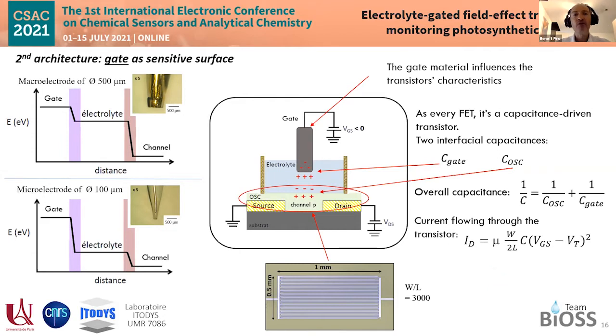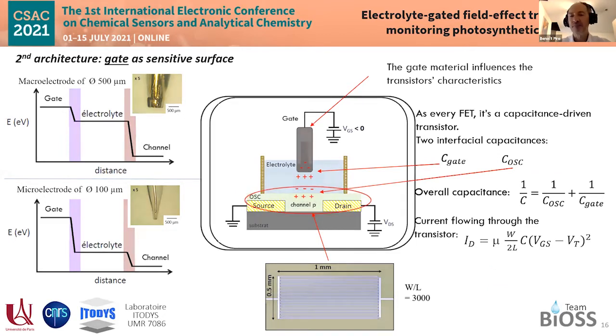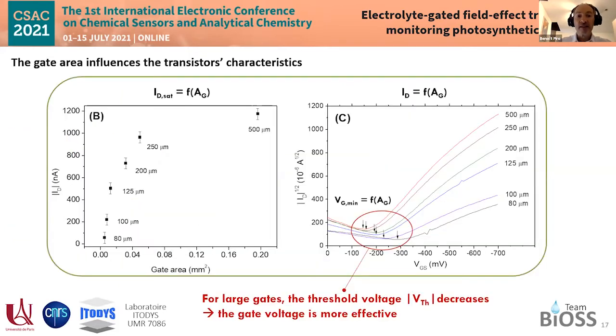Okay, and then we will focus on the functionalization of the gate. Now, it's illustrated here. If we vary the gate area, we can measure a change, all other parameters being constant. We can measure a large change of the drain current that way. And this is due to that reciprocal relation giving the capacitance, the overall capacitance of the device. So then, of course, for large gate, the current is maximum, of course. I will come back on that later.